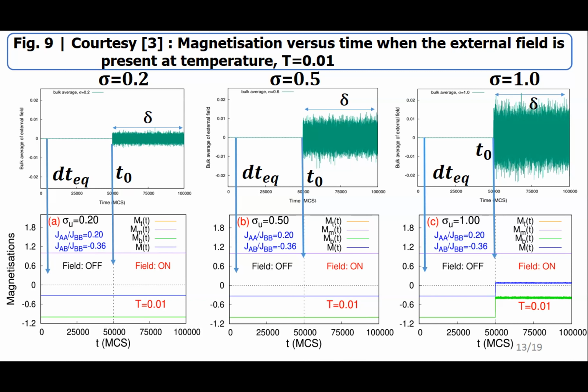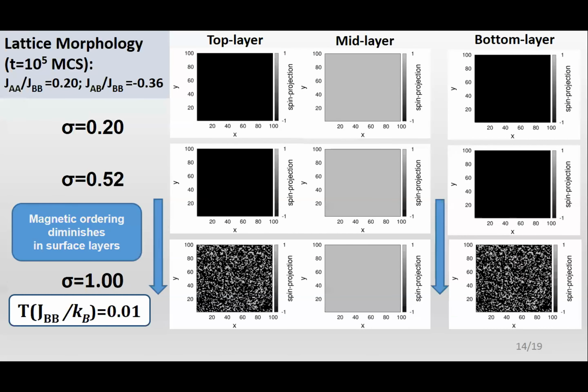The surface areas are mostly affected, and for sigma equal to 1.0, you see that the sublayered magnetizations actually approach the zero value. That is, the magnetic ordering is nearly destroyed. Just one more slide to understand what is happening here. The spin density plots are shown here. The lattice morphologies clearly tell us that the vanishing of magnetic order in the surface layers with sigma 1.0